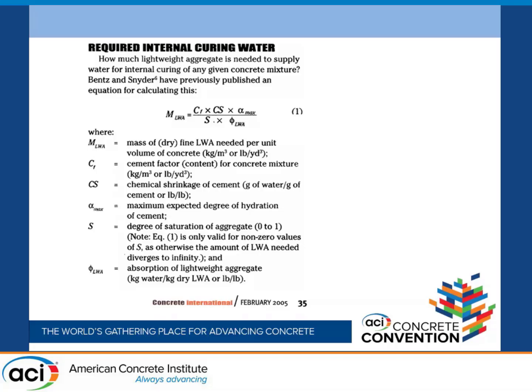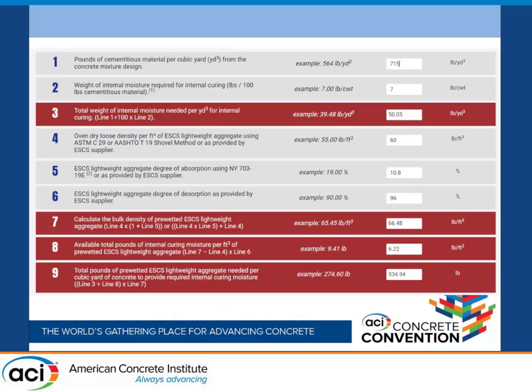Dale Bentz worked at NIST and had done a lot of research, and all of the subsequent research since he came up with this formula has confirmed that you replace a little bit of the normal weight fine aggregate with enough lightweight fine aggregate to provide an additional 7 pounds of water per 100 pounds of cement. That is the way that you provide internal curing.